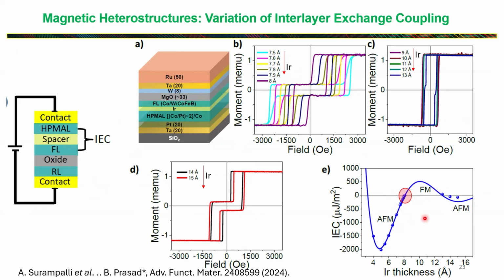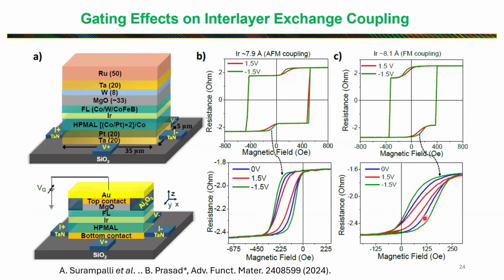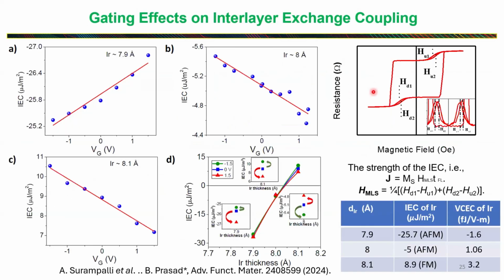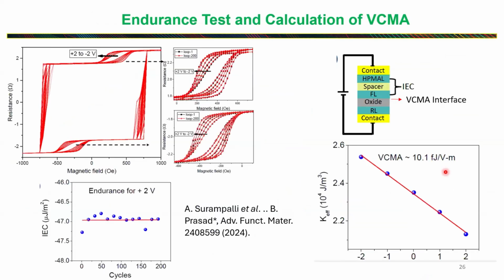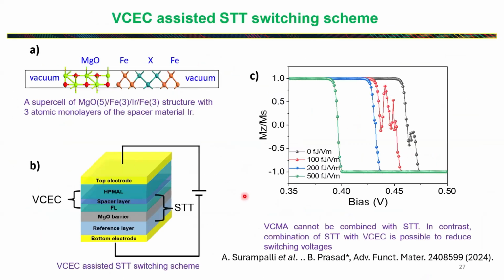And then there we apply the gate voltage. And we found that with applying the gate voltage, you can modulate this interlayer exchange coupling. And this is what we found. For the very first time, we demonstrated that with the MgO barrier, one can modulate the interlayer exchange coupling, and the VCEC coefficient is not that high, but it is kind of the proof of concept that yes, this does work. So eventually, if we can make this work with higher VCEC coefficient, around 100 or 200 femtojoule per volt-meter,